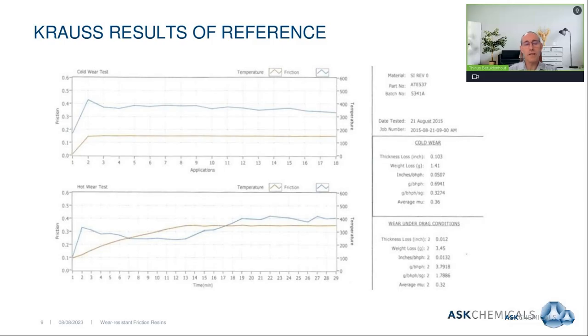We will now discuss the test results, the performance test results. First we look at the Kraus test results of the older technology, again what we call the reference. What you will see here on the screen in the top graph, and you will follow my pointer, is the red line, the temperature line, showing the 150 degrees Celsius test condition. You will see on the secondary y-axis on the right, 150 degrees Celsius, and the blue trend line being the friction coefficient on the primary y-axis.